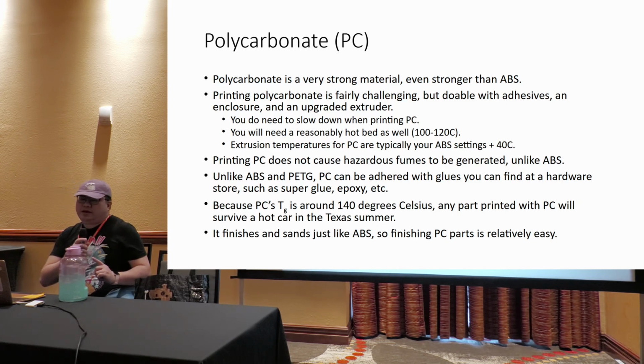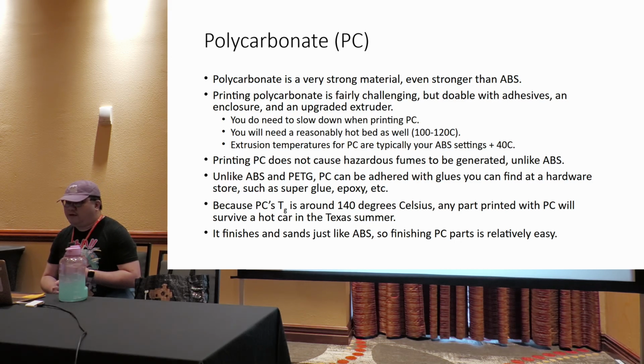And on top of that, because polycarbonate's glass transition temperature is 140 degrees Celsius, it is guaranteed to work in a hot car. Over the last summer, when we had all the really hot temperatures, I actually had a polycarbonate printed part sitting in my car in the middle of the day for 8 hours, and it never distorted. So, if they can survive that, they can survive everything.